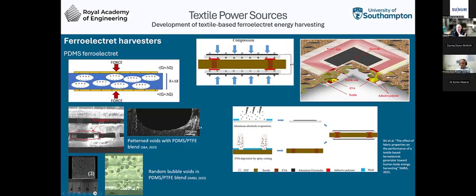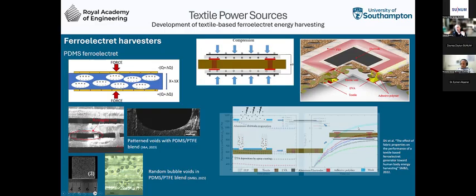The other thing we did was come up with a process where we could turn any normal textile into a ferroelectret generator. If we imagine an individual void here on the left, we can achieve this effect by adding an electret material in a film form either side of a textile. This part here is just like an annulus. It prevents the charge leaking out, because this is an area where we infuse a polymer across the textile. So we have our electrodes, our electret materials, and any textile can be sandwiched between these two electrodes. It's a very simple process where we charge up the surface of the electrodes, then bond them to a textile with that adhesive polymer annulus layer for sealing and bonding them together.